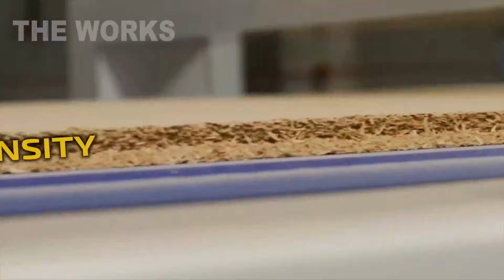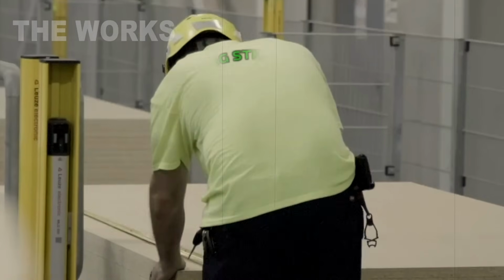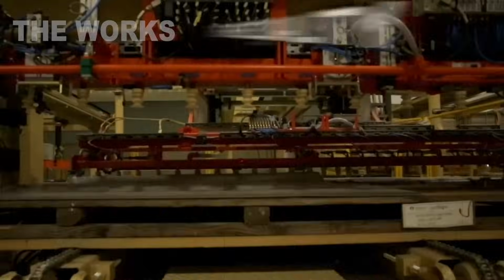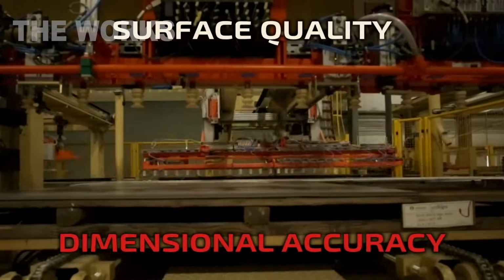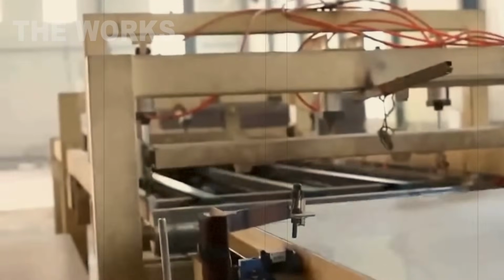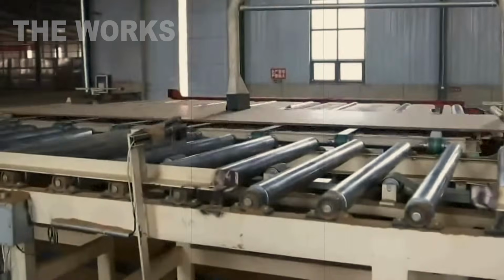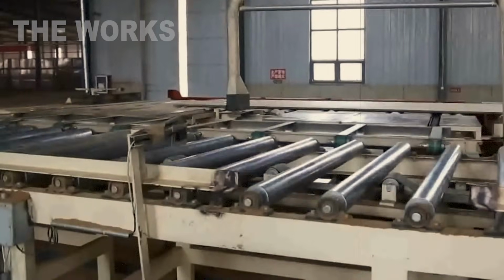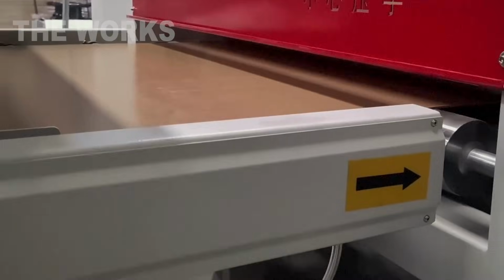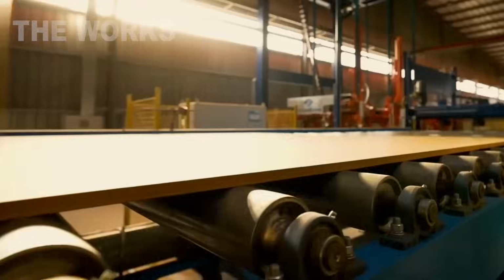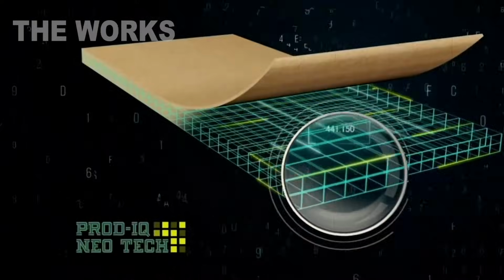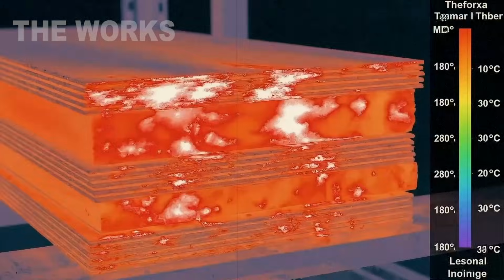Here they test its density, bending strength, moisture content, surface quality, and dimensional accuracy. Special instruments measure surface hardness, resistance to delamination, formaldehyde content, a crucial environmental metric. Board samples are tested on tensile machines, checking what kind of load they can handle. Moisture resistance gets tested by submerging samples in water for 24 hours and measuring how much they've swelled.